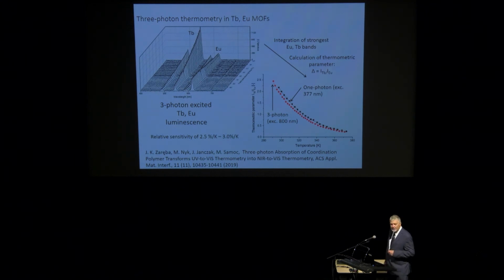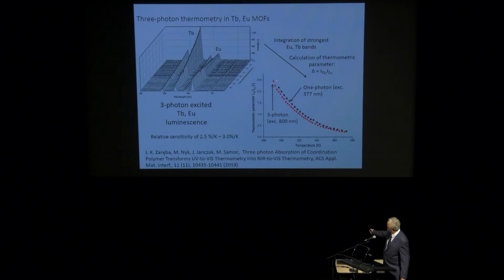And you can see that the changes of spectra are really very, very distinct. And these changes can be followed in two ways. Either exciting by one photon absorption in the UV, as most people do, or exciting by 800 nanometer laser. And again, in this case, we find that it's not two photon absorption, it's three photon absorption. But that doesn't matter. We still have very, very good spectra, and we still have the dependence of the spectrum, or so-called thermometric parameter, on temperature. This is a little bit different between the one photon case and the three photon case. These calibration curves are a little bit different, but there are good fundamental reasons for that.